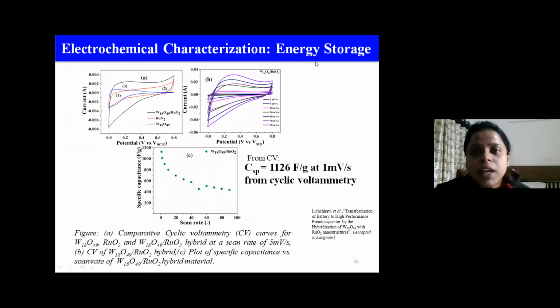Now we have conducted the electrochemical characterization for energy storage, and we can see that the W18O49-RuO2 nanomaterial is giving an EDLC behavior as a rectangular pattern. The W18O49 is giving a pseudocapacitive, pseudocapacitive battery nature, and the combined material again has a large surface area. From cyclic voltammetry, we have calculated the specific capacitance, and the highest specific capacitance is 1126 farad per gram at a scan rate of 1 millivolt per second.